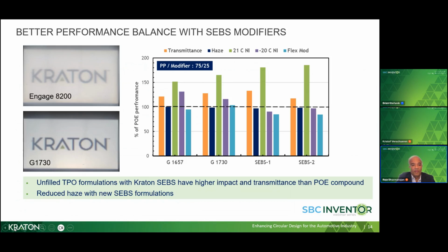So how does it look if you have an actual injection molded part? In order to do that, if you look at the illustration on the left, we injection molded a 2 millimeter thick plaque. One is a TPO compound containing the Engage 8200, and the second is the TPO compound containing our G1730 grade. So we have the Kraton logo at the back, and we did shine an LED light also to see how well the logo shows up. And you can see very clearly that with the SEBS solution, the letters are very clear and distinct, whereas with the POE solution, they are quite hazy.